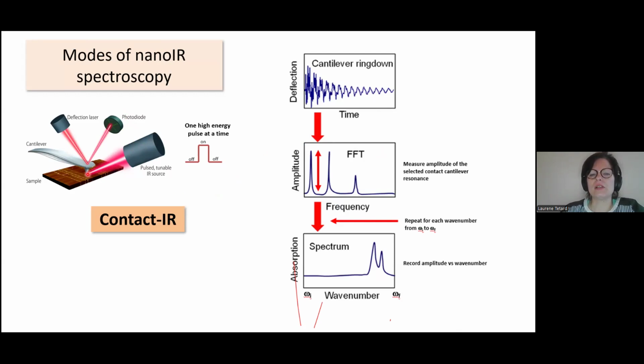And so the first iteration of this tool was to send a pulse of light and record how the cantilever is vibrating because of the response of the sample. So send a light pulse and detect the cantilever ring down like this. Then you can do a Fourier transform of the signal. You can select which frequency you want to study, and you look at the amplitude of that peak, for instance, the first one. Then you repeat that at every wavelength that you're interested to shine on your sample, and you can reconstruct an infrared spectrum.